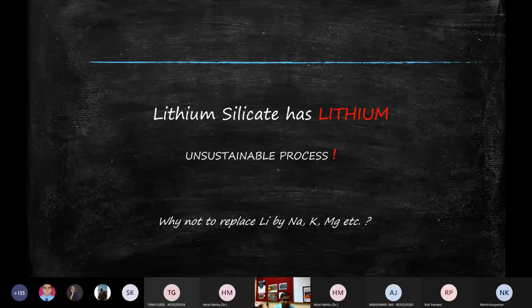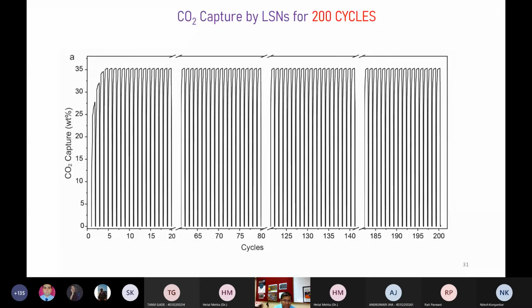So then the process is unsustainable ideally. But how do I make it stable? How do I make it sustainable? Another way of making it sustainable without replacing lithium is I keep using the lithium, maybe for 100 cycles, 200 cycles, thousands of cycles. Then the overall cost of the process will be low, right? Because I'm using the same material to capture a large amount of CO2. And that's what we showed here.